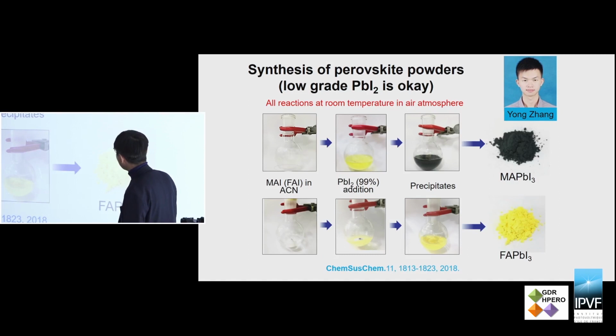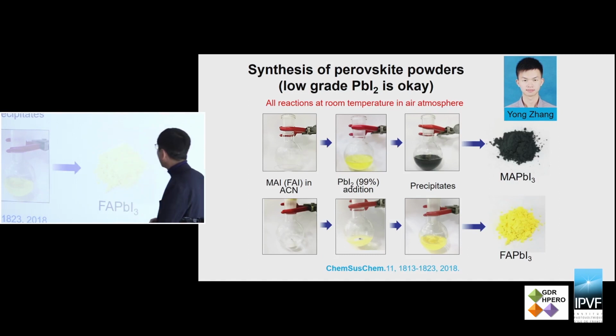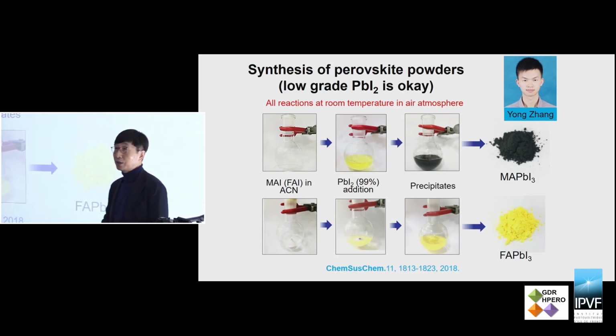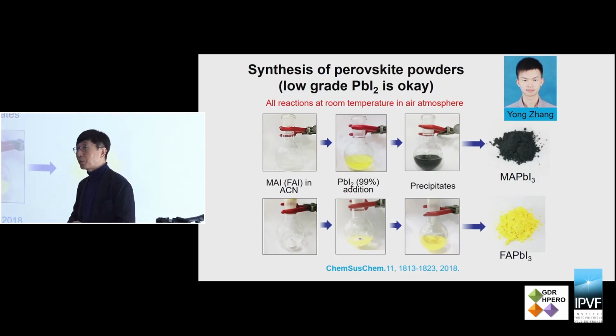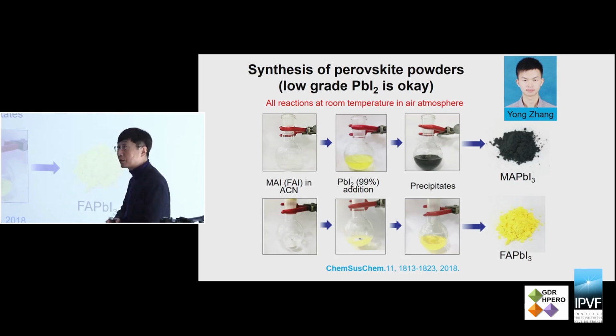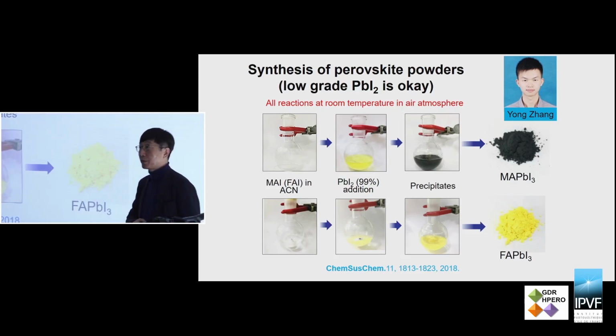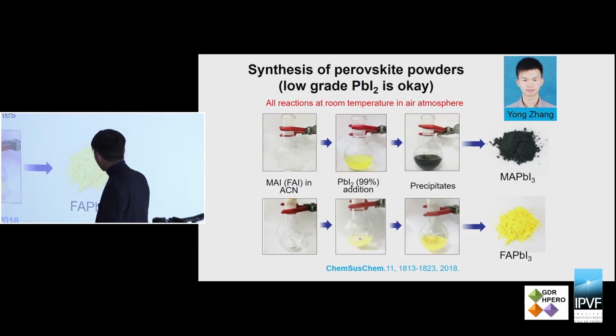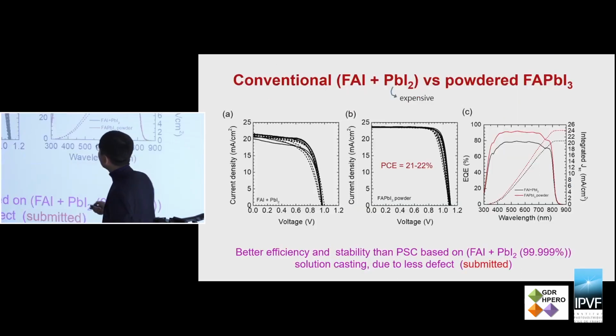However, in the FAPbI3 case, at room temperature, we get the yellow FAPbI3, which is delta FAPbI3, not the perovskite phase. Delta FAPbI3 is better than alpha FAPbI3 for the storage issue, because it is quite stable at room temperature. So we use the delta FAPbI3, and we compared this with high-grade PbI2, and this with delta FAPbI3 powder, and we continuously and reproducibly obtained over 21% efficiency.